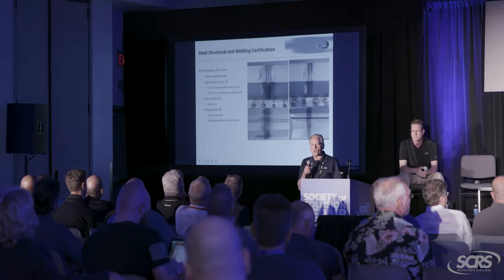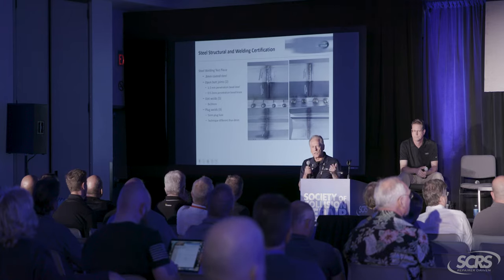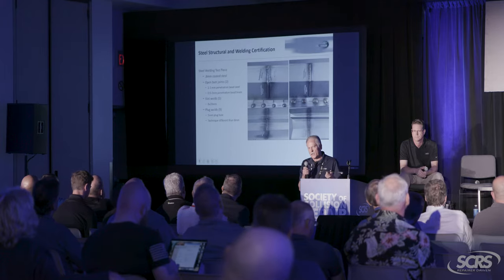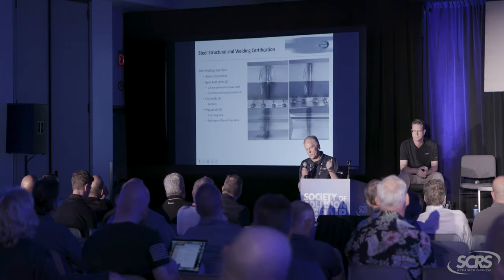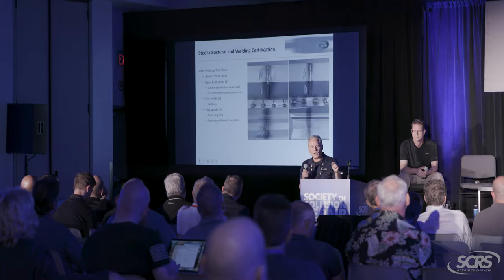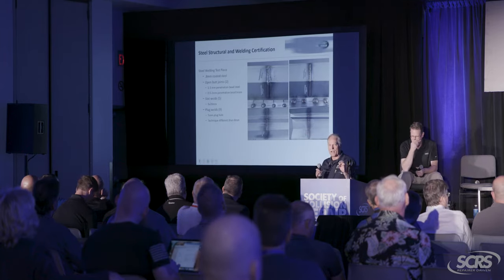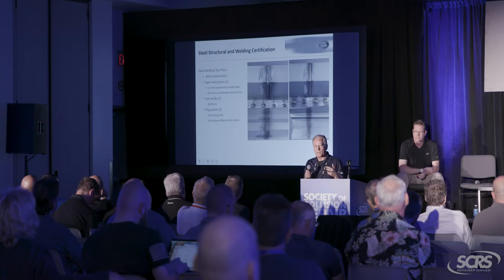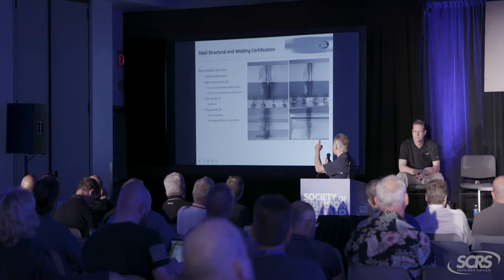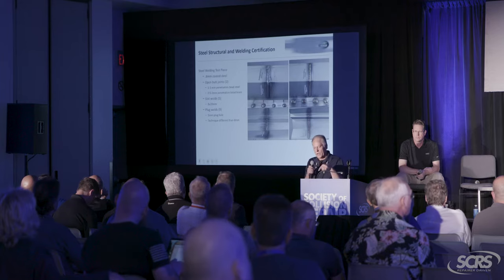We are doing that, I would call that in stitch continuous. So the technician starts on the bottom, pulls the trigger, hits it for 3 seconds, lets it cool, hits it again, lets it cool, hits it again, all the way up. Now, I know there's other ways of welding, but that's the only way that we found effective to get a no-flaw back, as you see in the lower left. On the back, it looks like somebody welded it from the inside. And the spec is, it has to be a minimum of 0.5 height, maximum of 1.5, so they've got to hit that, and all around the corners, there can't be any flaws.